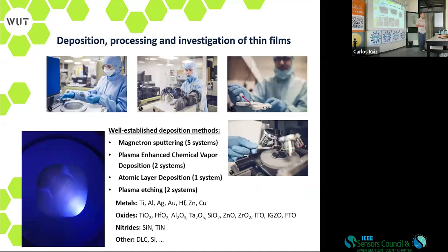So one of our premises is here, so people working there doing different material processing. In total, we have 5 sputtering systems available. One of them is fully automated, with 8-inch targets. This is a pure source of material, and there are 4 of them, so we can do co-sputtering, and multi-layers. But we have also a smaller system with 2-inch targets, also for sputtering. We have 2 systems for CVD, plasma-enhanced, and that's for deposition, but it can also be used for etching. We also have a system for atomic layer deposition, and two systems for plasma etching.